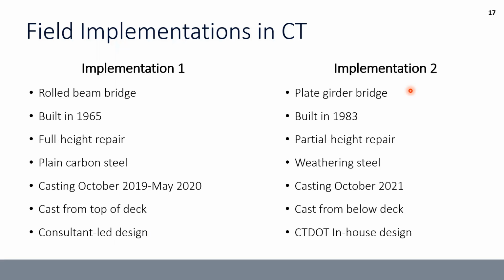This was a plate girder bridge from the 80s. One of the main differences was this is weathering steel. So before we went out and did this repair, we also did another series of those push-off tests to just make sure that all the equations that we were using for stud capacity were still applicable when we were working with weathering steel. And we found that they were.